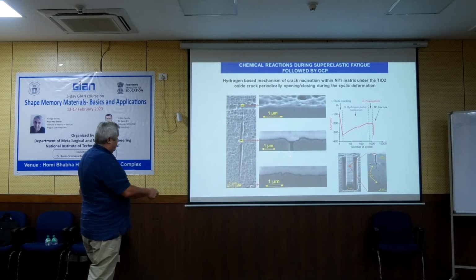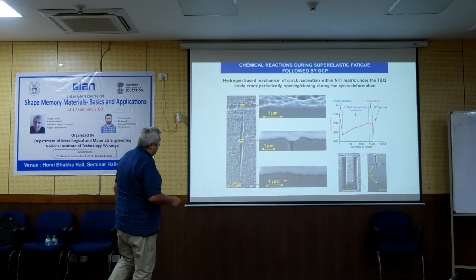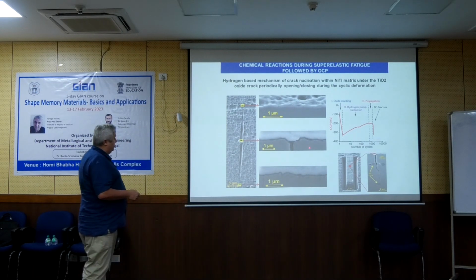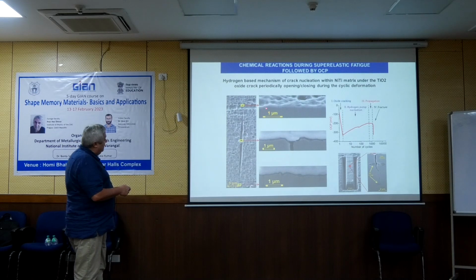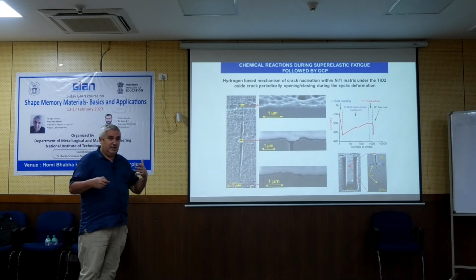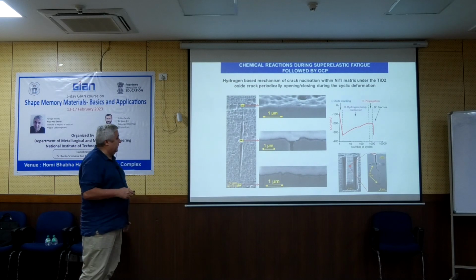This is shown here by the transmission electron microscope. We found that you have many oxide cracks, and under some of them you have cracks. This is already the cracks in the matrix. And there is perfect correlation between these oxide cracks and matrix cracks. So it is clear this was taken as evidence for this hydrogen pumping mechanism.